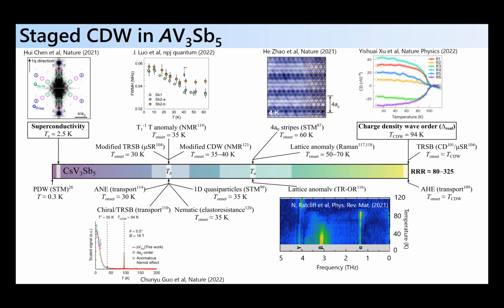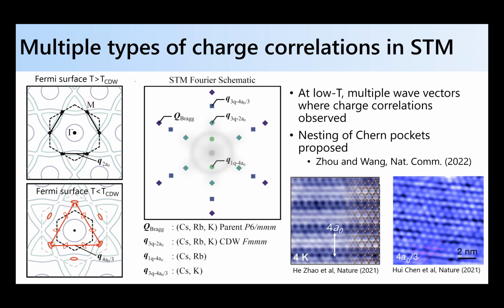But if you ignore all this stuff in the intermediate and you ask what type of charge correlations are sitting down at low temperature, really the probe that has explored this the best are STM measurements. And if you look at what STM sees in the low temperature state in the superconducting phase, they see 3 separate charge wave vectors. So the first is what they call 3Q2a0. That's just the charge density wave state I told you about. This is the staggered trihexagonal or the 2x2 enlargement of the unit cell. They also see the coexistence of what they call 1Q4A0. That's these charge stripes that are at least pinned at the surface, seen in STM. But then at low temperature, and I think the onset temperature here hasn't been carefully experimentally defined, there's an additional wave vector which is called 3Q4A0 over 3.